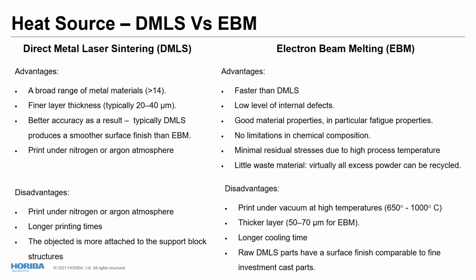Just a little bit to talk about the main difference of these technologies. Of course, both are proprietary, as are the acronyms. They both have the same goal, which is to sinterize the powder. The way one does it is using a laser, which is more precise than the electron beam. It requires a thinner printing layer bed of 20 to 40 microns, in contrast with the 50 to 70 microns of electron beam, which means the particle size of the powder is a little bit smaller when you use laser compared to electron beam. And then we have some implications which we'll discuss a little bit later.